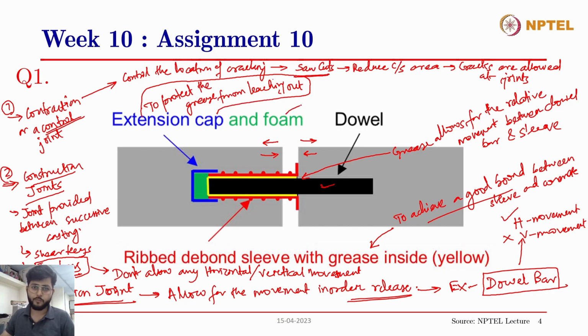And then there is a foam, which is this green portion, and this foam is basically a soft material, like any kind of softer polymeric material, like we have seen polyurethane forms of foam. So these kind of foams are provided so that they provide a good cushioning beyond the rebar, so that whenever there is an expansion, it has sufficient space for the movement, but it also doesn't allow for a free space, so that there is no entrapped air. Otherwise, that entrapped air, when it comes in contact with humidity, will affect the rebar, and that will cause corrosion of the rebar.